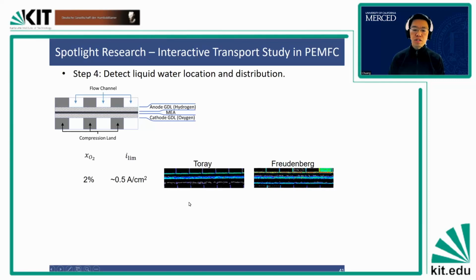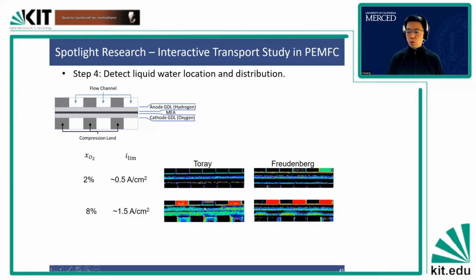But when we increase the current density, you can very quickly see that for the Toray material, again, the anode diffusion media is no problem. It's relatively dry. But on the cathode, again, the cathode is on the bottom side, the cathode diffusion media is pretty much filled with liquid water everywhere. But for the Freudenberg material, on the cathode diffusion media, you can see there's some water here, but no water here. Some water here, no water here.